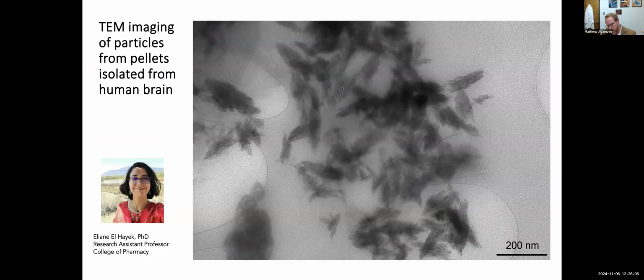And when we isolate the plastics from the brains and from the livers, and we do a good job of digesting them and using benzene to pull all the lipids away, we see images like this. And this is Eliane El-Hayek. She's been doing a lot of this imaging. And we see these flakes, these shards, and they're easy to find once you do the digestion. We're jumping through a lot of hoops now to prove that these are plastics, but I can say to you every test we've done,